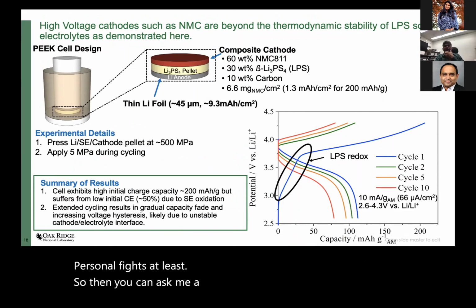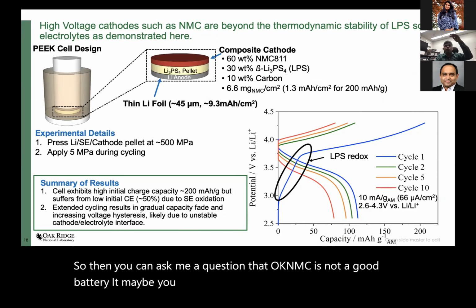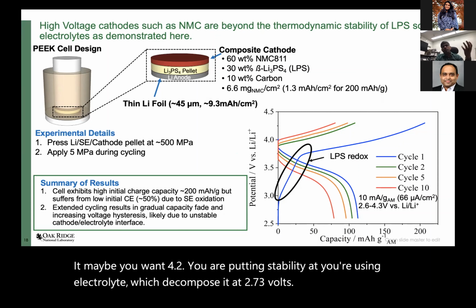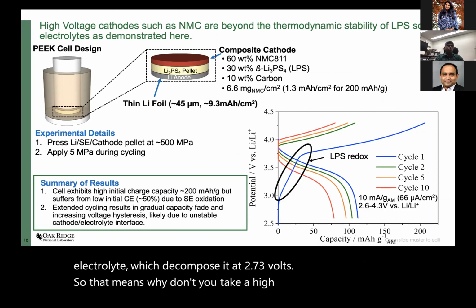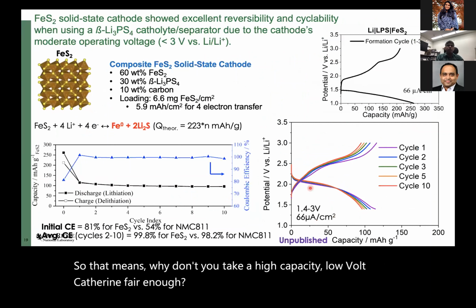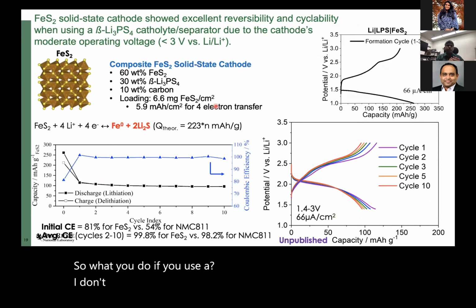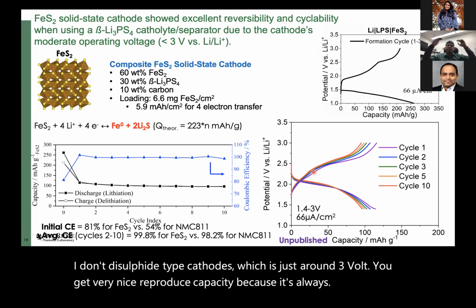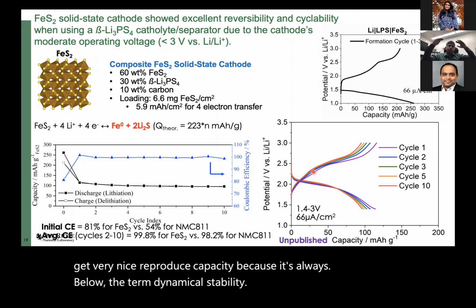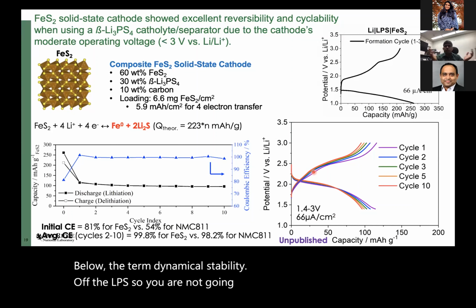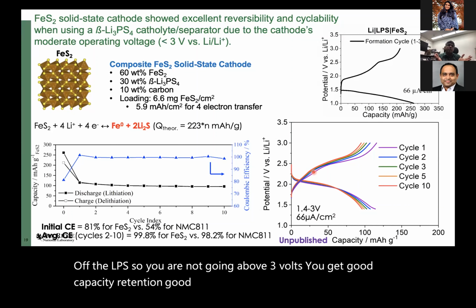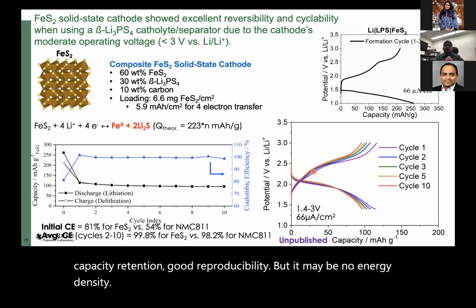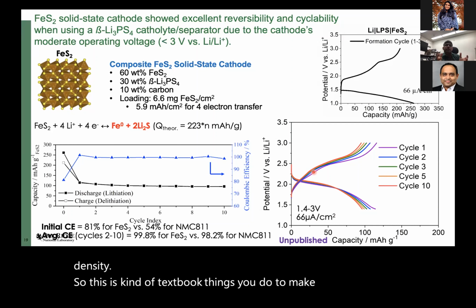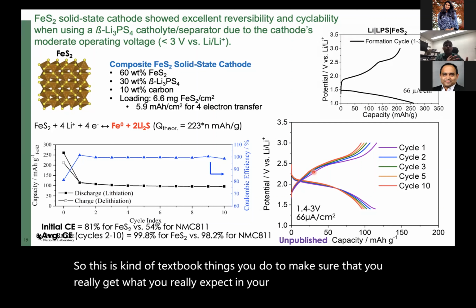So then you can ask me a question that, okay, NMC is not a good battery. You want 4.2 volts, but you are using an electrolyte which decomposes at 2.7, 3 volts. So that means, why don't you take a high capacity, low voltage cathode? Fair enough. So what you do, if you use iron disulfide type cathodes, which is just around 3 volt, you get very nicely reproducible capacity because it's always below the thermodynamic stability of the LPS. So you are not going above 3 volts. You get good capacity retention, good reproducibility, but it may be low energy density. So these kinds of textbook things you do to make sure that you really get what you expect in your electrochemical signature by changing the cathode chemistry.